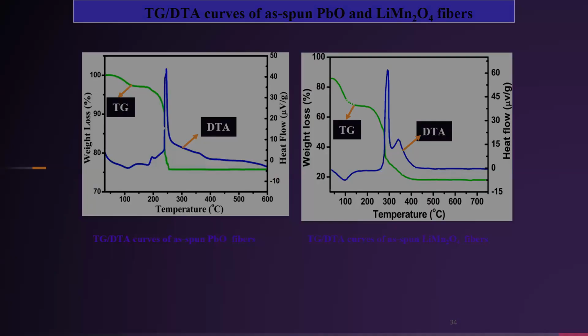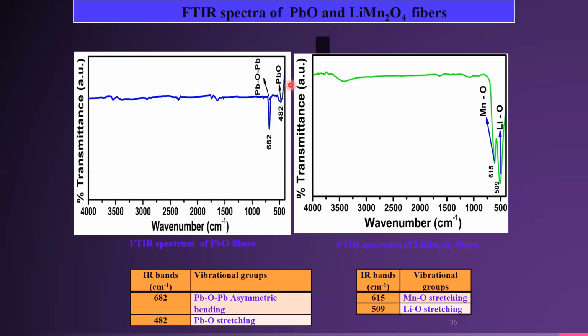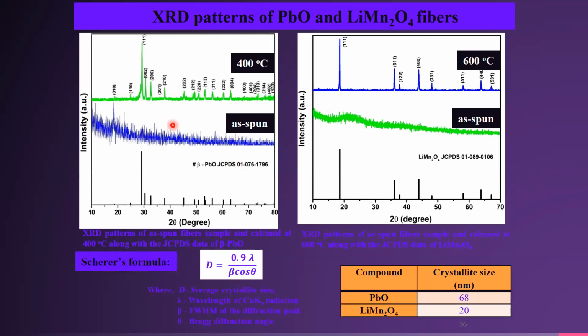All the observed IR band positions of lead oxide and lithium manganese oxide nanofibers are in good agreement with the reported literature values, which confirms the formation of lead oxide and lithium manganese oxide nanofibers. The XRD patterns of the as-spun nanofiber samples show peak-free patterns, confirming the formation of an amorphous phase. The sample obtained at 400 degrees centigrade shows diffraction peaks that, compared with the JCPDS data file of beta PbO, confirm the formation of phase pure orthorhombic crystal structure.